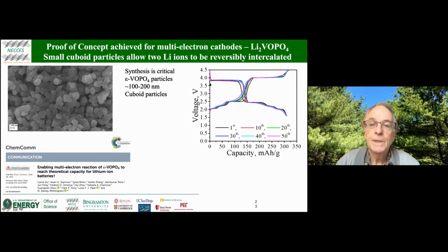So you can see, using this material, we get 2 plateaus, vanadium 5 to vanadium 4 just under 4 volts, then vanadium 4 to vanadium 3 at just over 2 volts here. Then you see there are some ordering transitions in here, which apparently have no effect on the cycling ability. In fact, in this range, this material has the same capacity at 1 C rate as at C over 50 rate. So very, very high power capacity there, but that's not the case at the high voltage.